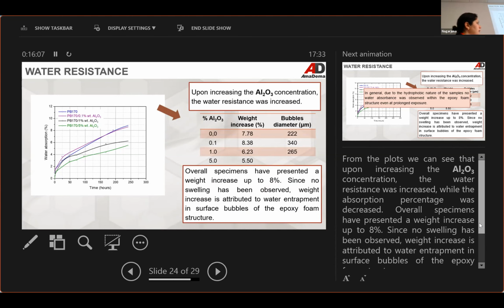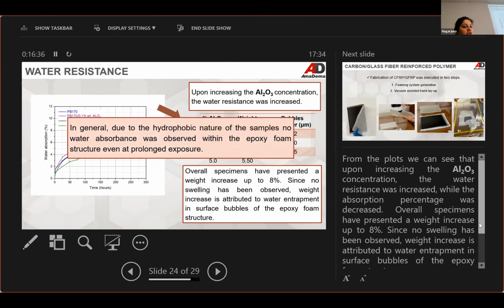What is noteworthy is that even though the specimens have demonstrated an increase in weight, no swelling was observed, and this led us to conclude that this weight increase is attributed to water entrapment within the surface bubbles of the epoxy foam specimens used, since these had some roughness to them. And in general, these hydrophobic foams do not really change when they are exposed to moisture, which is very good when we're dealing with aerospace and structural applications, of course.